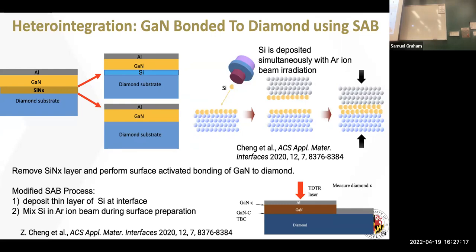We've done a little bit more on this study with a material called gallium oxide bonding to diamond, but let's stick with this study now. So I tried to get rid of the silicon nitride. And what we found is that we could use a very thin layer of silicon deposited inside the chamber and do the activation and bond it, or we could take a silicon containing metal organic species, embed it inside of the ion beam, and it would break some of the hydrogen off. And so you can sort of mix it in and bond the gallium nitride to the diamond. All right.